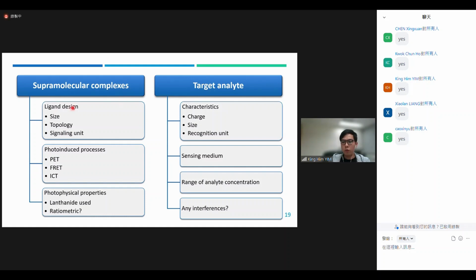For example, if you are going to prepare a complex, you have to think of the ligand design: the size of your supramolecular complex, the topology, whether you want a cage, a cube or a helix, and the signaling unit. Then you have to think of the photo-induced process, whether you want PET, FRET, or inter-ligand charge transfer. You also have to think of the expected photophysical property of your complex. For example, which lanthanide you are going to use: if you want green emission, you use Tb, or if you want red emission, you use Eu. And you need to think of whether you want to make a ratiometric sensor. That means you probably have to incorporate two emitters.